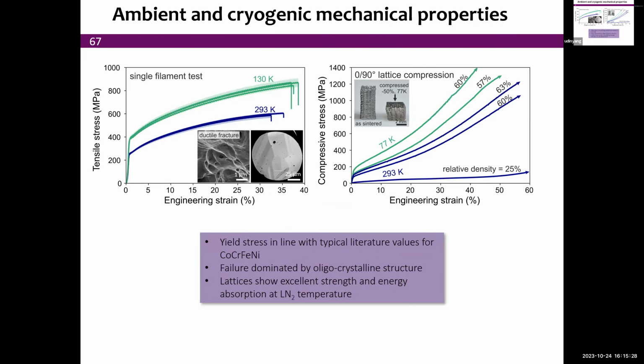And so we did mechanical testing on single filaments, so the extruded filaments. Here are the room temperature properties: yield stress, a lot of strain hardening, 30% engineering strain in tension. So this is clearly a ductile material, and it's very similar to the properties that are reported for cast high entropy alloy of that composition. Where those materials shine is in the so-called cryogenic temperatures, with 130 K here. We see, of course, a high yield stress as expected, but still a huge amount of ductility at cryogenic temperatures, unlike, say, BCC materials that become extremely brittle once you're cryogenic. So this is a good combination of strength and ductility at cryogenic temperatures.